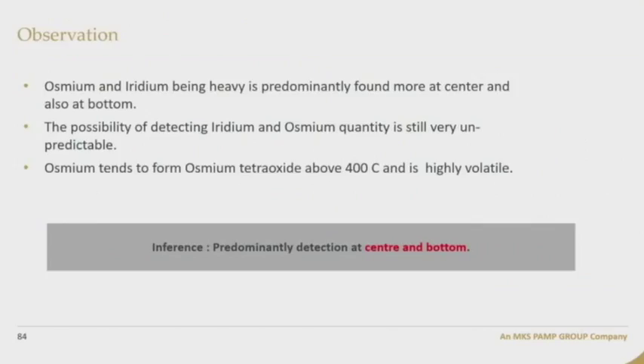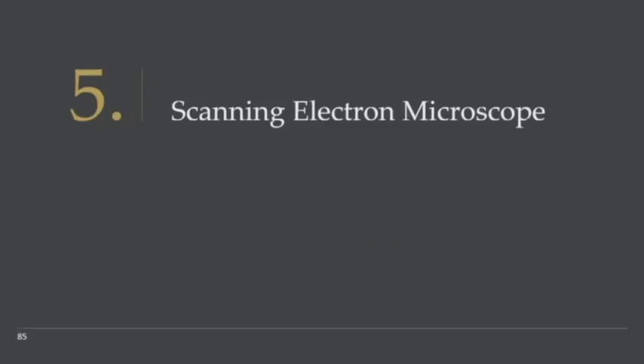So what we could conclude, osmium and iridium, being heavy, are predominantly found more at the center and also at the bottom. The possibility of detecting iridium and osmium quantity is still very unpredictable. Osmium tends to form osmium tetroxide above 400 degrees and is highly volatile. So we really need to go further into this study, but this preliminary study shows that whenever we find osmium, we should have more analysis at the center and bottom.